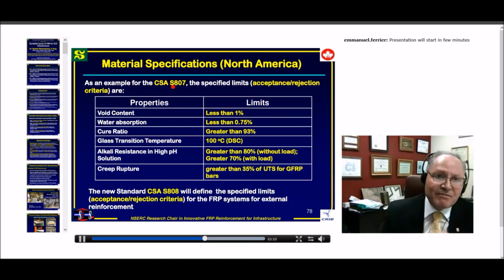This is an example of the limits that we have from the S807: void content less than 1%. And this is really very good. I can tell you most now about internal reinforcement, about rebars. All of them, as I explained before, if made by pultrusion open die, in general they are getting 0.5, 0.6. But with closed die, sometimes they're getting 0.1, 0.2%, because as I told you, there is no contact with the atmosphere, the void content is really less, and also taking care about the speed and everything to avoid creating any cracking from thermal stresses and so on.